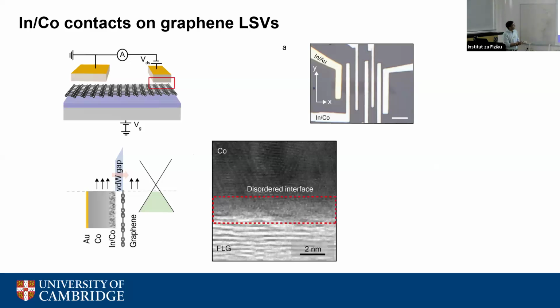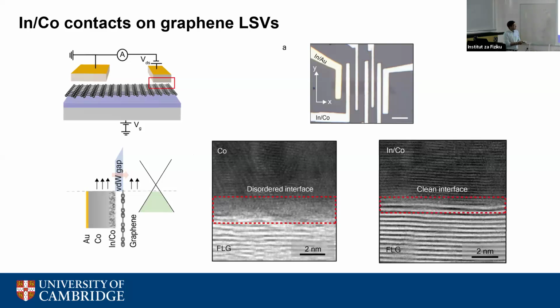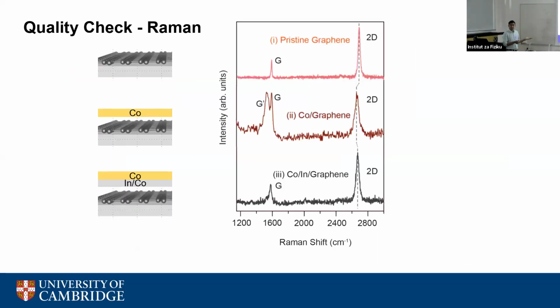First we deposited cobalt, which is the ferromagnet and, as I said, is very reactive. And you can see the interface is highly disordered. If you deposit indium cobalt, you can see it forms a very clean interface. It is like a van der Waals contact with a vacuum gap between the metal and the semiconductor. And we also use Raman to test our devices.